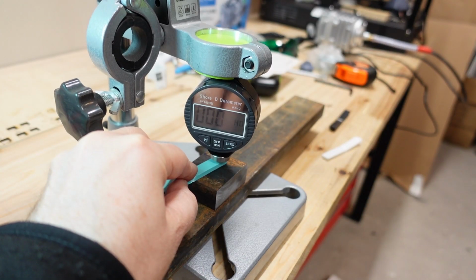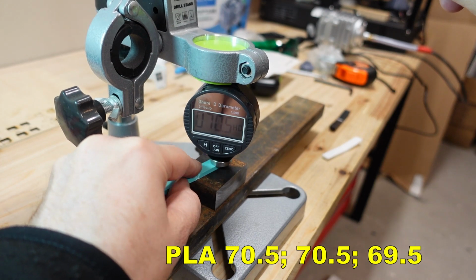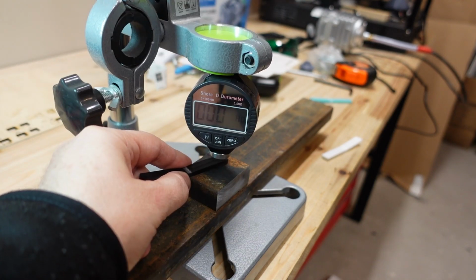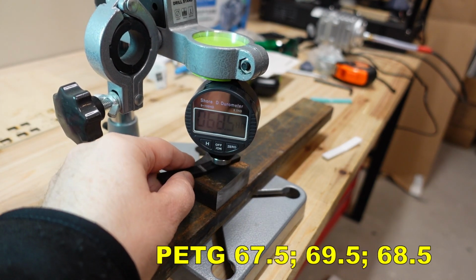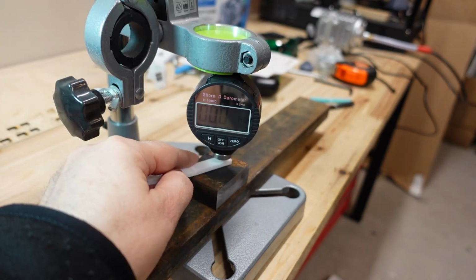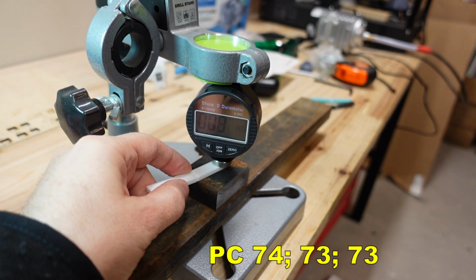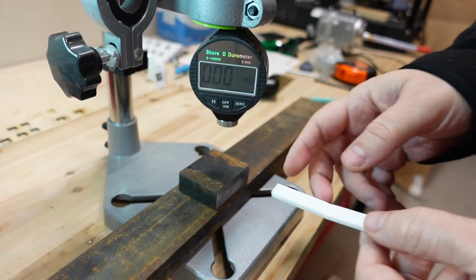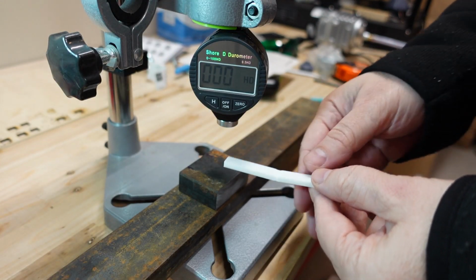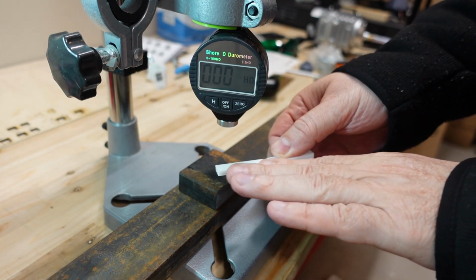PLA 70.5, 70.5, 69.5. PETG 69.5. Polycarbonate 74, 73, 73. So polycarbonate was the hardest, and everything was measured perpendicular to the layer direction.